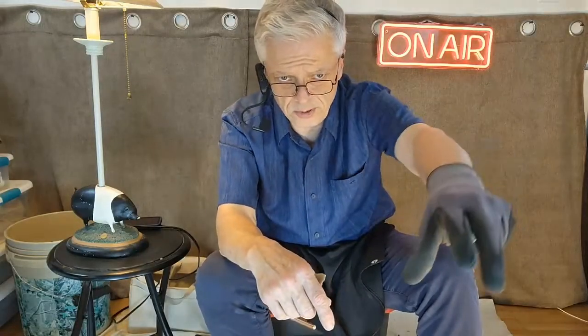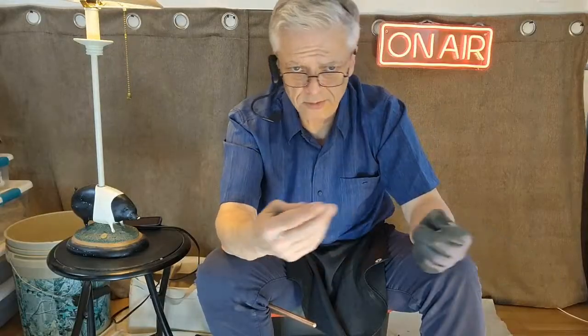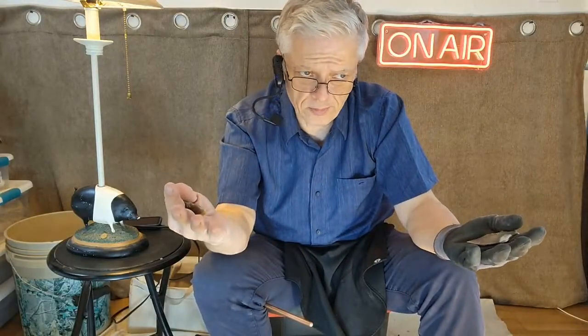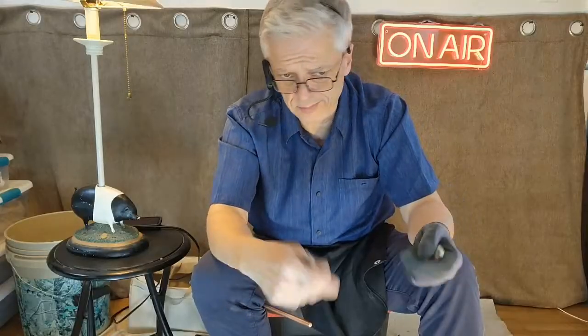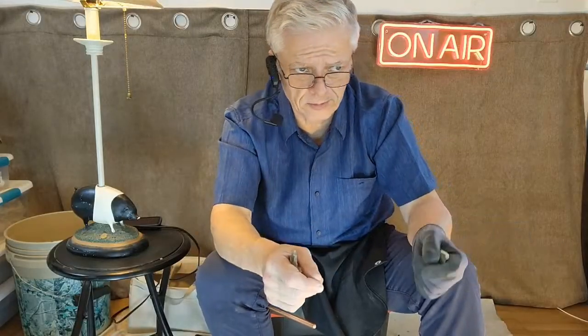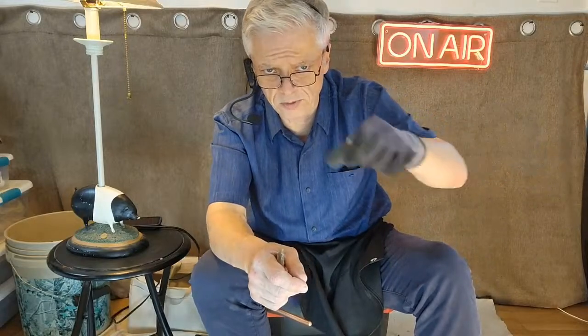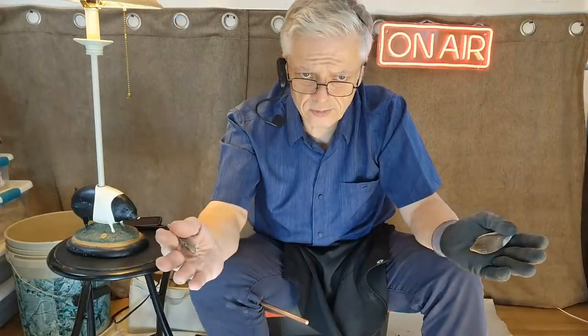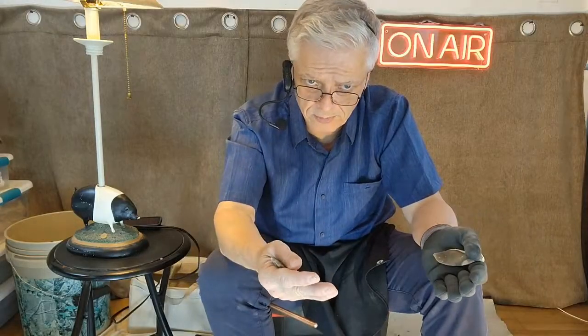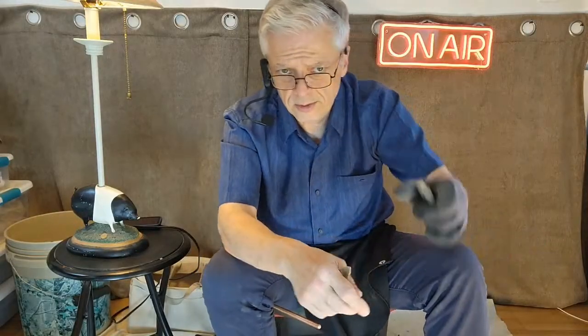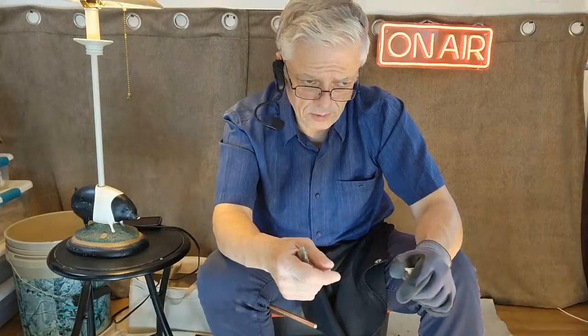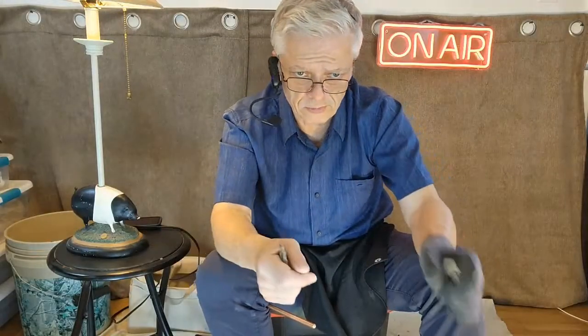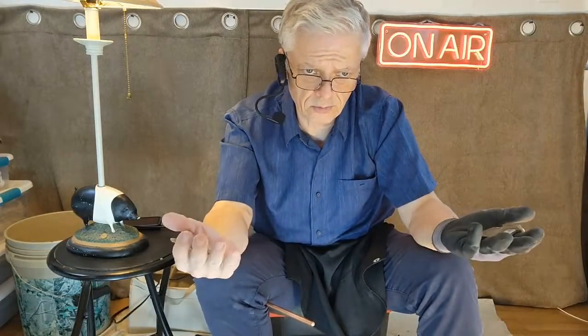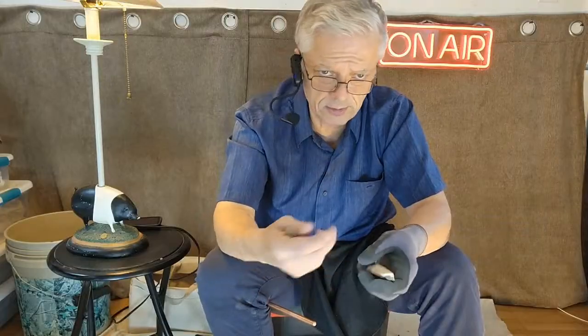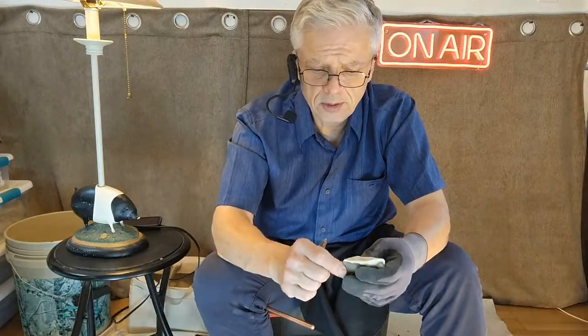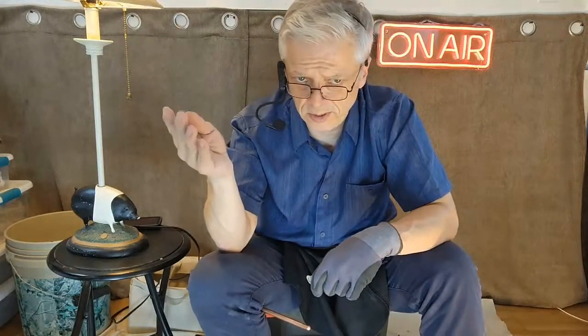You take your stone, put it in the roaster at 200 degrees for 24 hours. Wait a certain amount of time before you take it out. Don't take it out fast, maybe 3 hours, so it cools down to room temperature. Take it out, weigh it, and compare the weights before and after. If there's no loss in weight, it's dry. But if you see a drop in weight, that means there was water in it. Try it again for another 24 hours. If it stays the same weight, then you know the 24 hours was good enough. Then you know how long it takes to dry your material. You've got to be in the experimental mind frame.